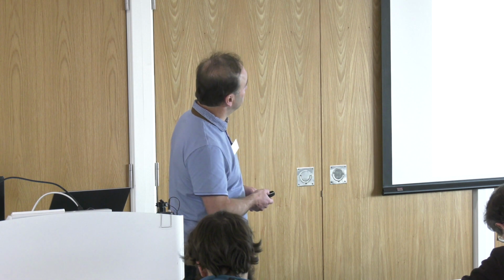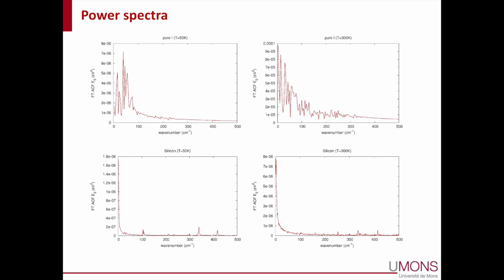Now we're trying to understand what are the phonons, what are the killer modes for perovskites, and you can do it in a similar way as I've shown for organics by working in the time domain and doing the Fourier transform of any function. In this case, it's the band gap, and essentially we end up with something with a lot of activity in the low frequency domain, below 100 wavenumbers. This is a region where you expect longitudinal optical phonons in those ionic crystals to be very strong, and it's likely that some of these features correspond to those phonons.